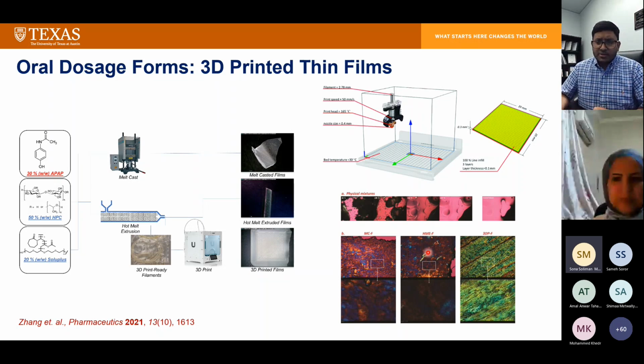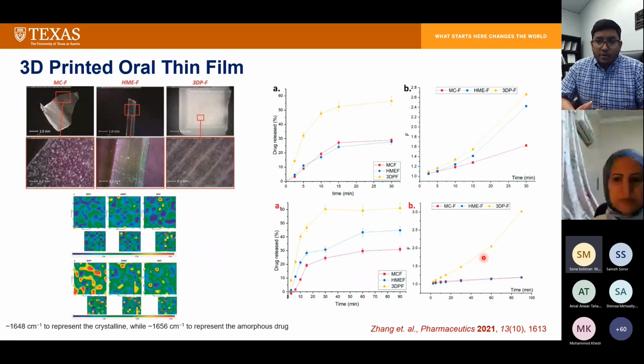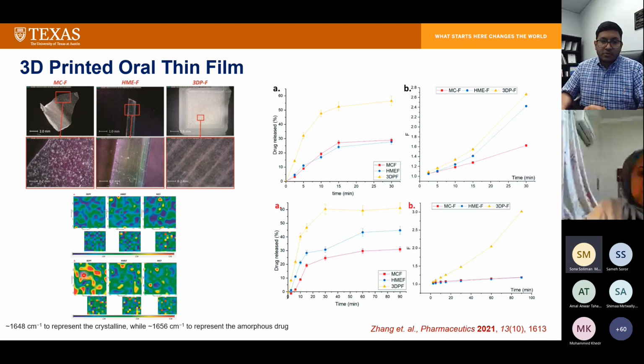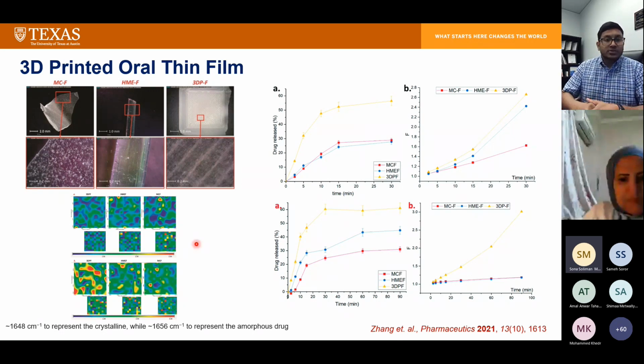Similarly, the hot melt extrusion based film showed better homogeneity in terms of the drug distribution. But when we compared with our 3D printed dosage form, we found that drug distribution was much better in our 3D printed film. When we went for this advanced physicochemical characterization, especially the advanced surface analysis of the drug distribution, we found that in our 3D printed films, drugs were present in amorphous form, and the distribution of the amorphous drug onto the surface of interest was more homogeneous compared to the films printed by other technologies, right? And that was mainly due to the high shear mixing of the extrusion and then the 3D printing process.